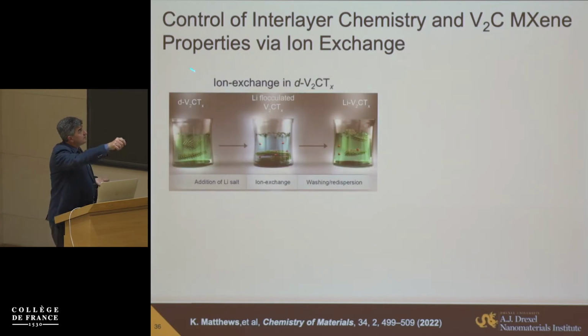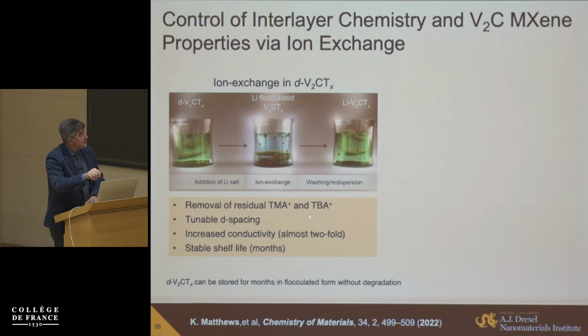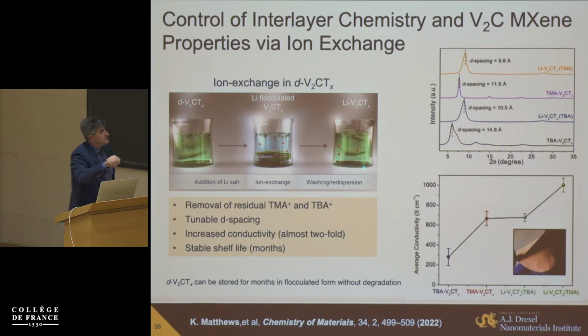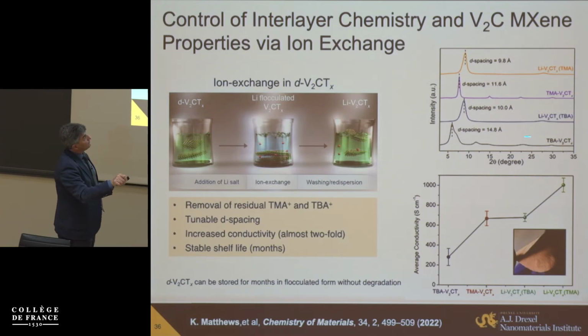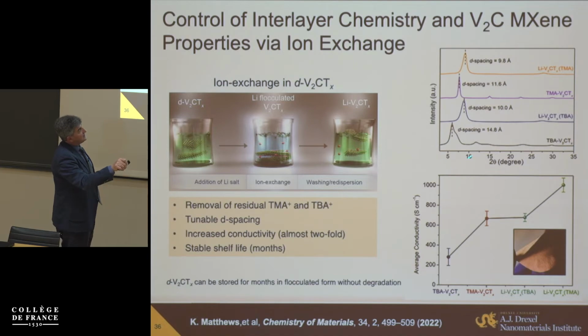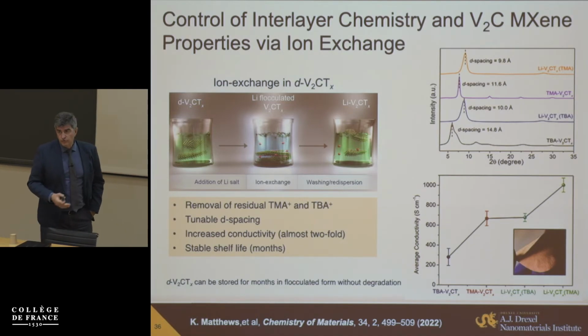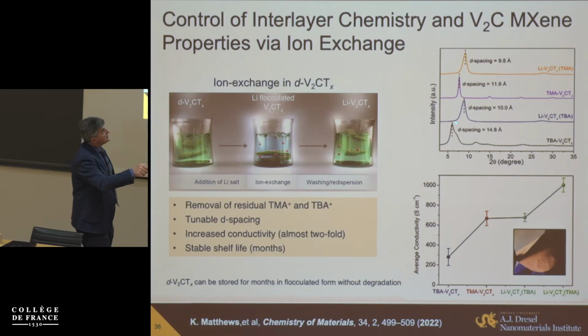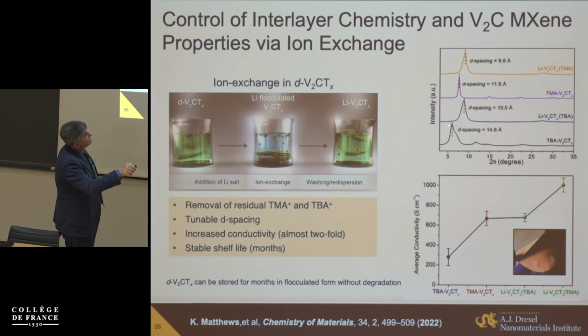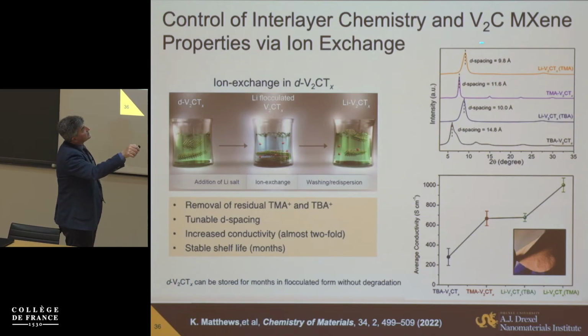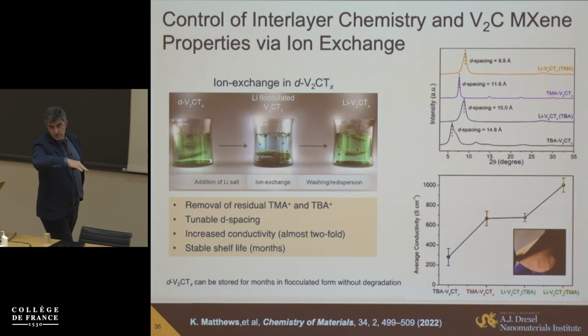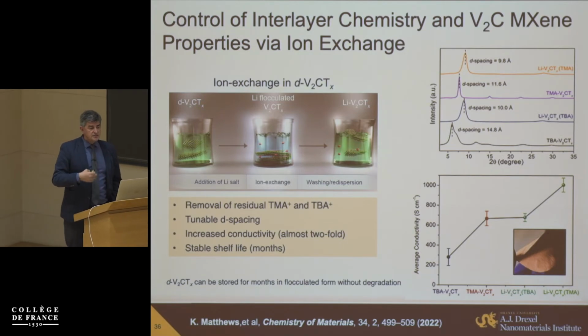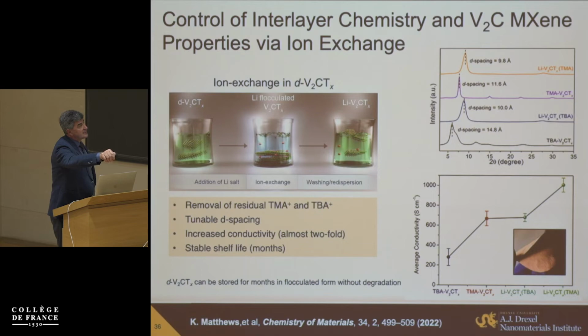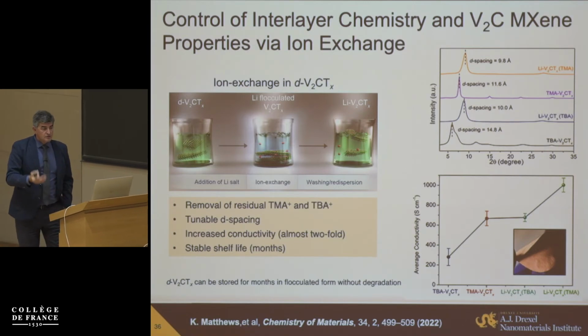So what we do is delaminate it initially with tertiary amines, but then we replace TMA and TBA with lithium. TBA and TMA are very common delaminating agents also for oxides, clays, and dichalcogenides. When you go from TBA-delaminated V2C to lithium, we decrease the spacing significantly because we get smaller ions. But moreover, lithium coming closer to the surface, not allowing more water to come in, makes the material much more stable and increases its conductivity. So we go from about 270 to over 1,000 Siemens per centimeter. So again, we can play these games.